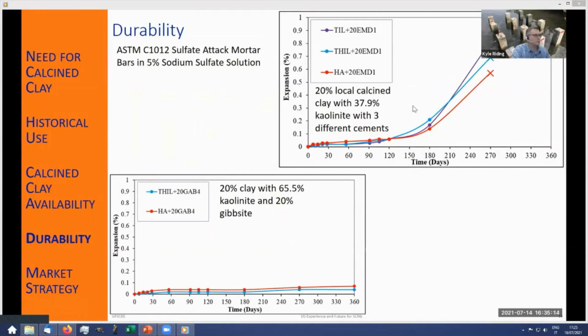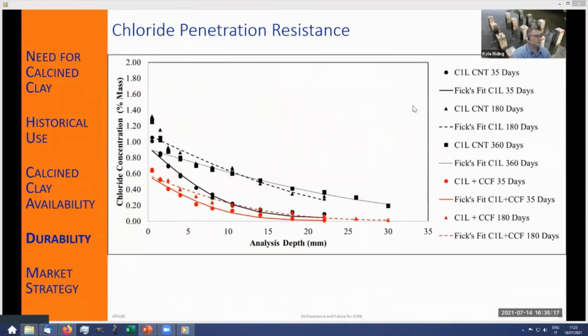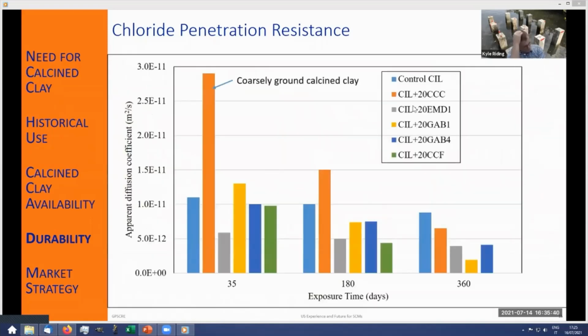The local material that we're producing here in Florida and in Georgia gives you improved durability from a chloride standpoint, so corrosion resistance. Again, another reason why the material is used. So we're getting a performance improvement out of this calcined clay material when it's used with limestone cements. You get this synergistic reaction for durability. We can see that with pretty much all the clays that we investigated. You get an improvement in the diffusion coefficients, meaning you get reduced chlorides and reduced corrosion from use of this material. Even in the materials that aren't very finely ground, you get an eventual improvement versus the Portland cement control.